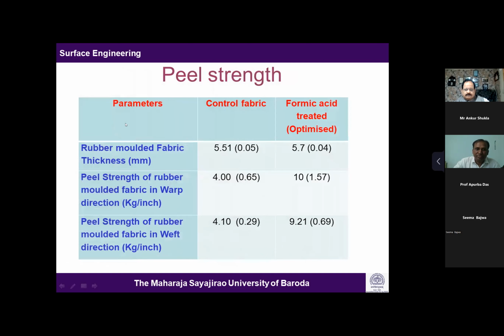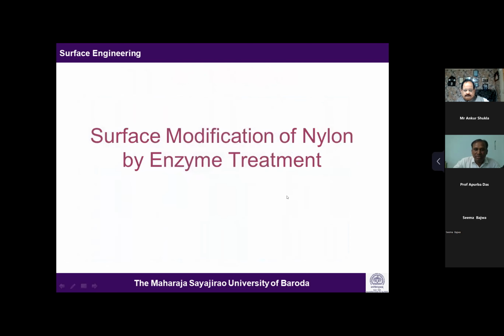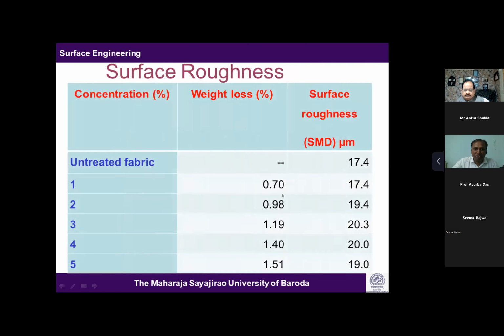So this is the peel strength. We could see that after the modification, the treated sample shows a higher peel strength value. The next one we did was nylon with enzyme treatment. We used the protease enzyme, which can act on the amide groups. It was estimated based on the weight loss of the nylon with the treatment.